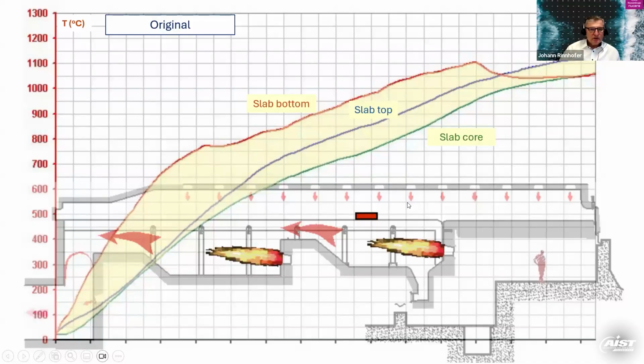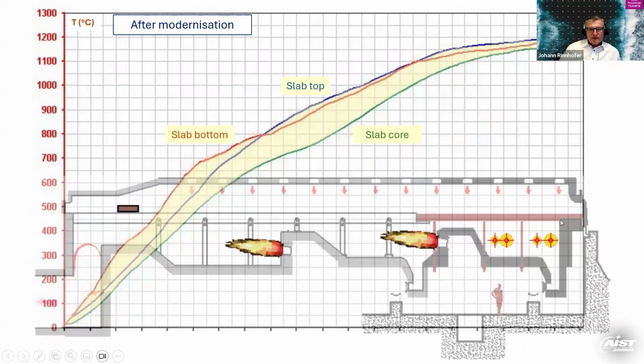So what is the situation after? It looked like that. So we had changed the soaking hearth, as I said, into an actively heated lower zone. And now we can reduce the temperature of the slab surfaces, top and bottom, and avoid scaling to a higher degree than before. We can actively heat the bottom of the furnace in the soaking zone. That means we are still increasing the temperature here, and we have a really good temperature difference, a very low temperature difference at the end, which is very beneficial for the rolling process and the quality of the end product. So that's in short the option we have now, because we rebuilt the furnace completely to a different heating strategy.